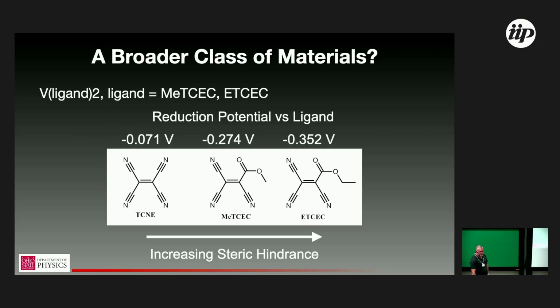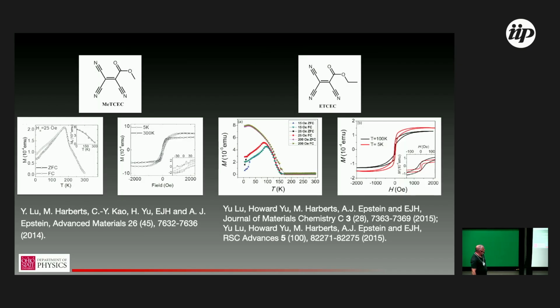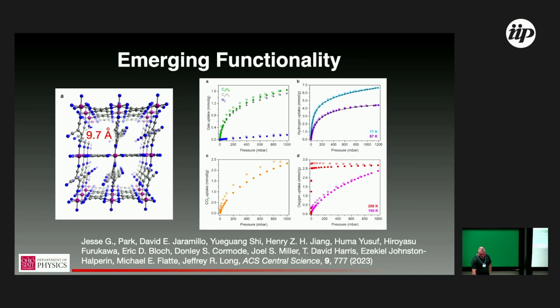You can also change the ligand, which we have looked at in the CVD regime, and the DC magnetic properties are interesting. We're varying both the electronegativity and the bulkiness of the ligand, as you can see in the cartoon up here. So it's not so straightforward from this one study to disentangle these two effects, but you can make what I called at the time the second best molecular-based ferromagnet, which is to say it still has room temperature ordering. You see this characteristic peak structure at around 150 Kelvin. That points to some interesting physics in the underlying magnetic ordering.